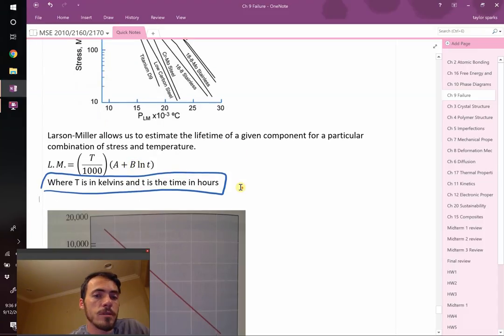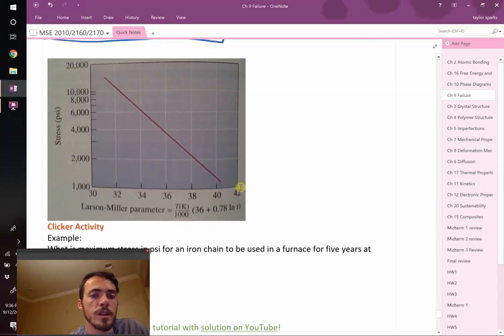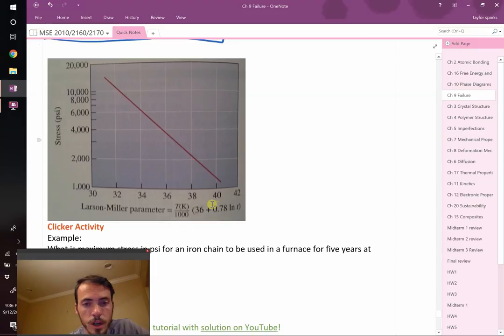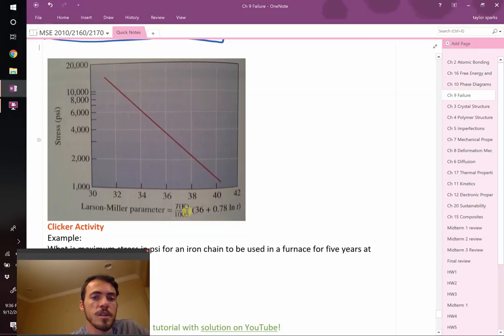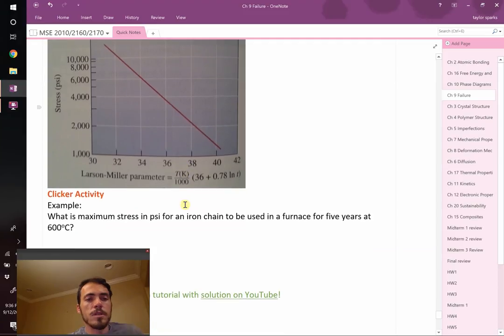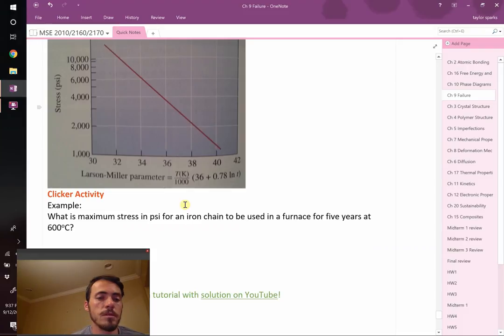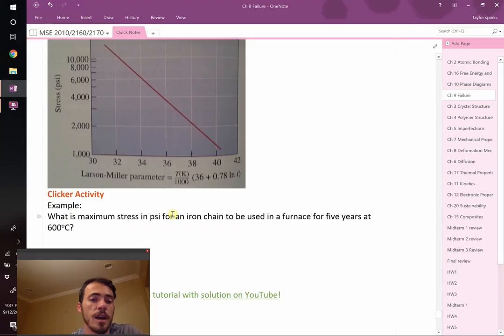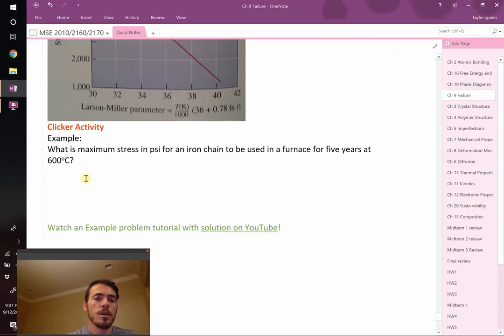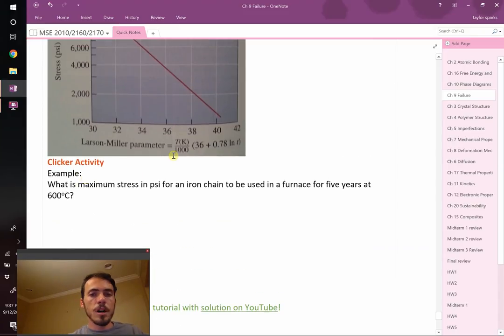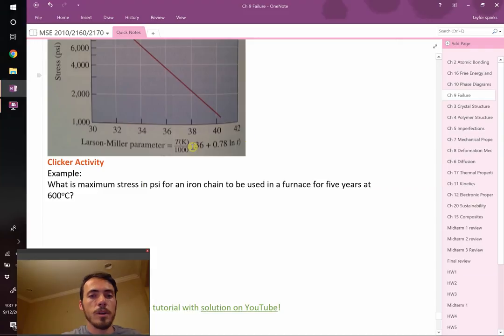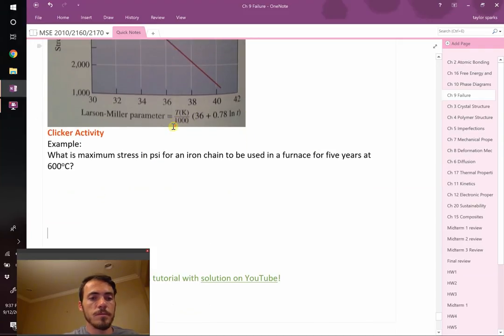So it has goofy units. First thing to realize is that the temperature is in Kelvin and the time t is almost always in hours. Unless it says otherwise, that's the assumption. So Larson-Miller parameter has this expression. You take the temperature that you want to test it at, divide it by 1,000. You multiply that by the quantity of a plus b, these are constants that depend on whatever is given for the plot, times the natural log of hours. A typical plot might look something like this. Here, they show you the stress at which something will fail at. The x-axis is your Larson-Miller parameter. They show you what the two constants are. It's 36 and 0.78. Since they haven't said otherwise, this t is in hours and temperature is in Kelvin.